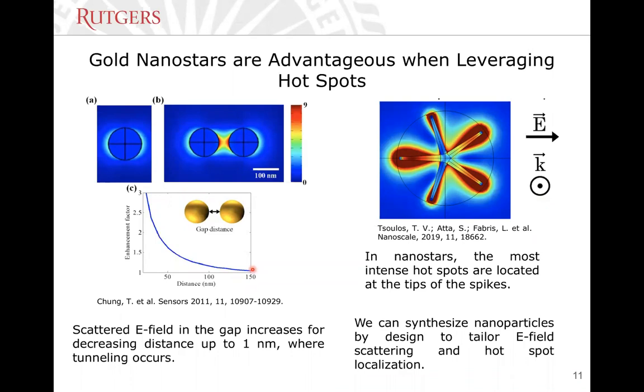You have to have absolute control of the kinetics and the thermodynamics of the reaction. You have to control the surface charge of the nanoparticles, concentrations of the linkers, temperature, and concentration of the nanoparticles present. So it takes some time to really optimize it. And we did a lot of molecular dynamics simulation studies to really understand the conditions. On the other hand, we found out that if we make nanostars, they carry their own hotspots. So this is relatively more convenient because we synthesize the nanoparticles and we don't need to assemble them with